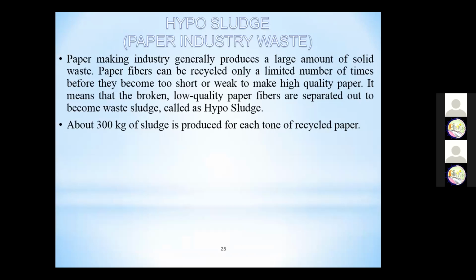Paper industry waste. The paper making industry generally produces a large amount of solid waste. Paper fibers can be recycled only a limited number of times before they become too short or weak to make high quality paper. It means that the broken low quality paper fibers are separated out to become waste sludge called hypo sludge. About 300 kg of sludge is produced for each ton of recycled paper. So this is a very important line: 300 kg of sludge is produced for each ton of recycled paper.